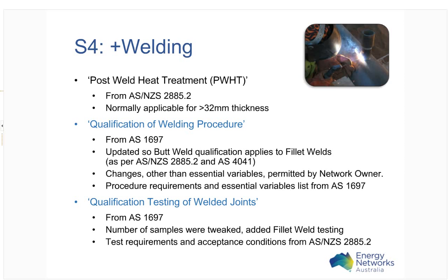Some of the numbers that have increased in that area are around the tensile testing that now requires a test for the smaller diameters. The pipe ranges that are applicable here are underneath 60.3 millimeters diameter and smaller, between 60.3 and 323.9 millimeters inclusive, and then the really large stuff that I doubt many people are really using, over 323.9 millimeters. So that relates back to the procedures and also the essential variables listing that gives a fair range of applicable procedures that can be used on distribution networks.